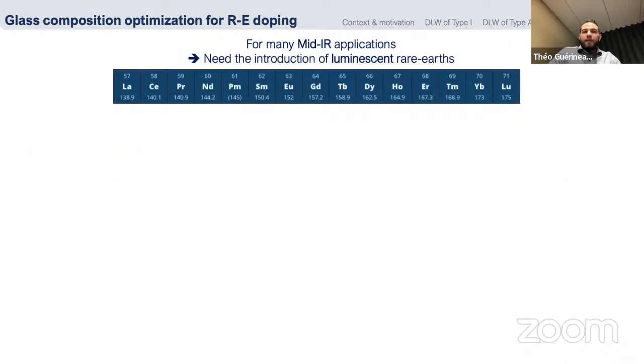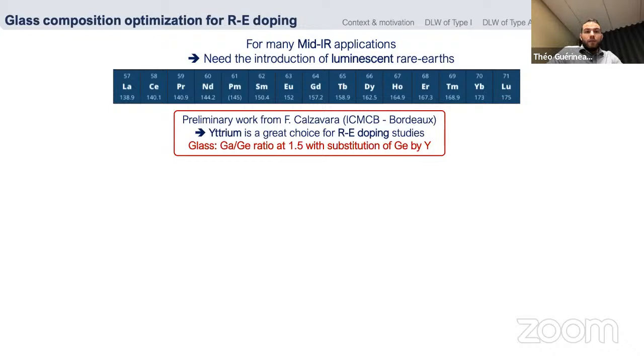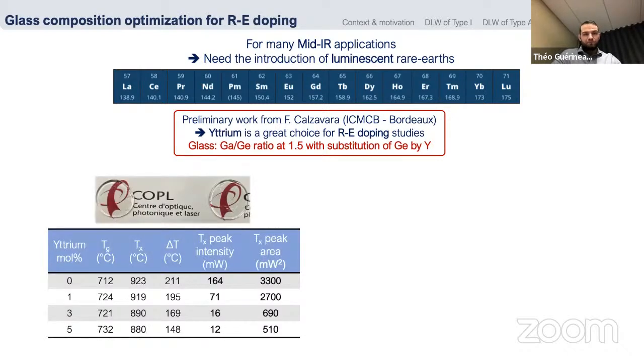For many infrared applications, we need to introduce luminescent rare earth. But what has been shown in the preliminary work by Florent Calzavara at the ICMCB is that yttrium is a very good choice for rare earth doping studies. Of course, yttrium is a non-luminescent rare earth, but it helps us a lot to simulate how the rare earth will impact the glass properties without impacting the optical losses. So we fixed the ratio between gallium and germanium at 1.5, as I showed you earlier, and then we substituted the germanium by the yttrium. We synthesized 3 glasses with 1, 3, and 5% of yttrium.